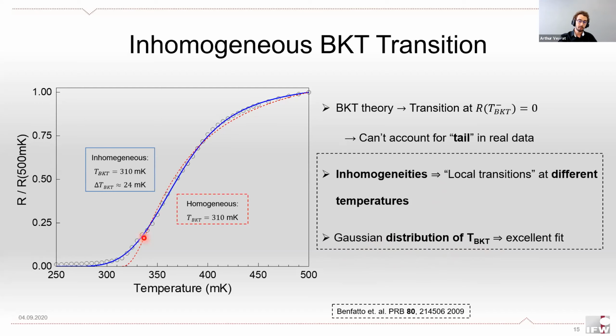This is what we did here in blue. You can see that we have a very good agreement with our data, and this for only a quite minor spread of transition temperatures. So this is a good proof that we have a BKT transition happening in our sample, even though we have quite thick samples, so we're very far away from a single or even a few layer limit.